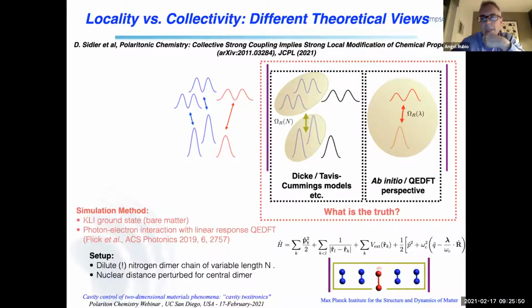To do that, what we took is a set of nitrogen N2 molecules, up to a maximum of 10 molecules, as I illustrate here. And then something which is really important for you to capture is we have a set of n molecules, and I take one of them, it doesn't need to be the one in the center, it can be anywhere, and I deform it, I perturb it, which is what you do in chemical reactivity. And you want to know what is the modification of the properties of that molecule due to the fact that it's embedded in a big cloud of molecules, and those all interacting with the cavity mode.